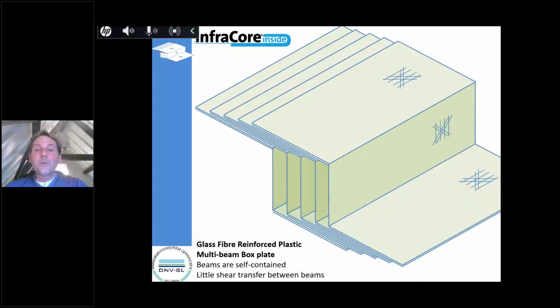In order to be able to stack these preforms, you have between these perpendicular webs, you have non-structural foam. So in the first step of our production phase, we take a foam preform, we wrap it, we surround it with dry fabrics, then we go to the mold and we stack these preforms next to each other.